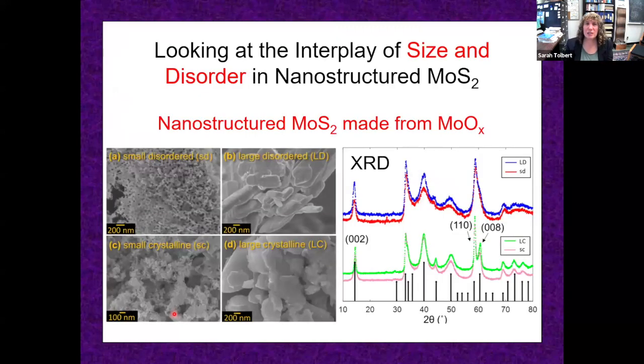So we'd like to use this system to learn about the effects of size and disorder on controlling fast charging. And we take advantage of the fact that we make our sulfide from an oxide to control the disorder. So we control the size by the size of the oxide that we start with. If we want little MoS2, we use little moly oxide to start. And if we want big MoS2, we use big moly oxide to start. But if we want to make it disordered, we do this conversion at a low temperature.